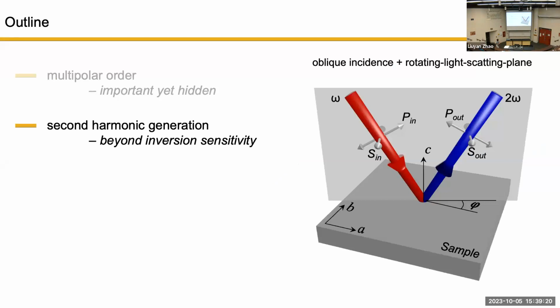After that, I hope to introduce you to a technique that has been around for a long, long time, which is second harmonic generation. That is a frequency doubling process. Once you shine a red light onto your material, you get a blue light coming out. This is a process that materials allow to happen. But the conventional wisdom is that this process only happens when the material breaks the so-called inversion symmetry. In my introduction to this part, I hope to convince you that we can push the sensitivity of SHG beyond this conventional wisdom. Nowadays, we can actually measure SHG out of materials with inversion symmetry. And utilizing this, we can see many things that we were not able to see before.